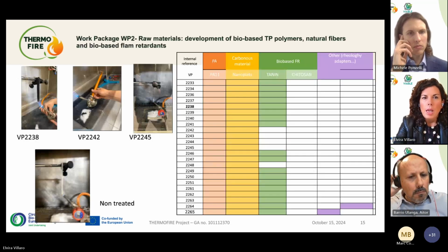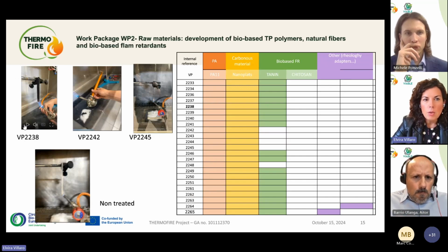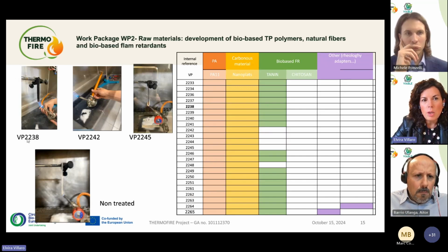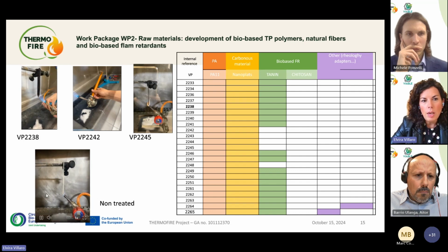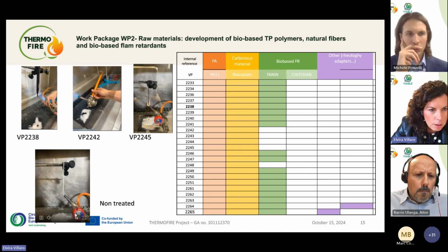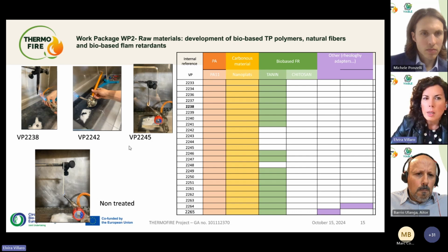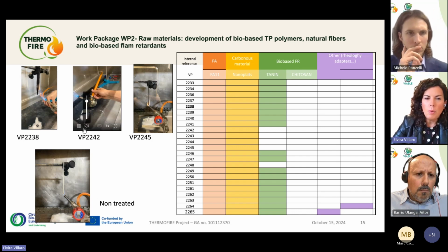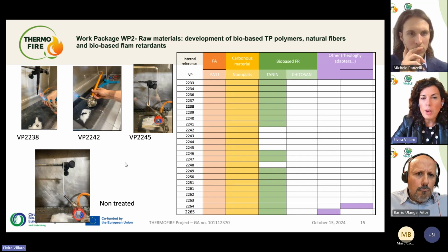Okay. So here we can see some videos in which we can see the performance of the composites we are testing until the moment. We can see, for example, this one, which contains carbon materials, bio-based flame retardants. If we compare it to the performance of the neat polyamide without any treatment, we observe a significant difference. In the time after flame exposure, the performance we are achieving is significantly shorter. It's the time that we need for the UL94.